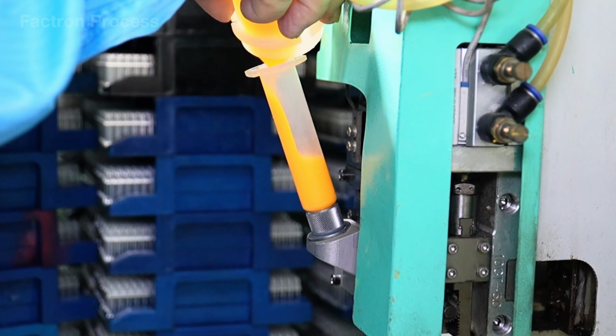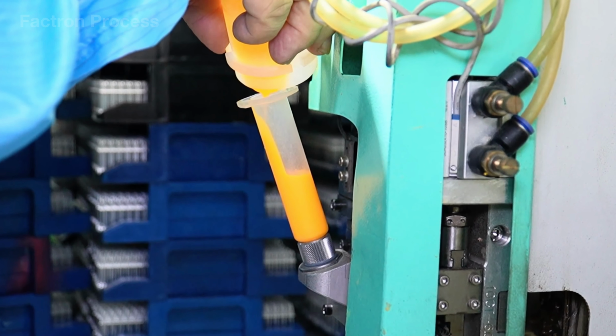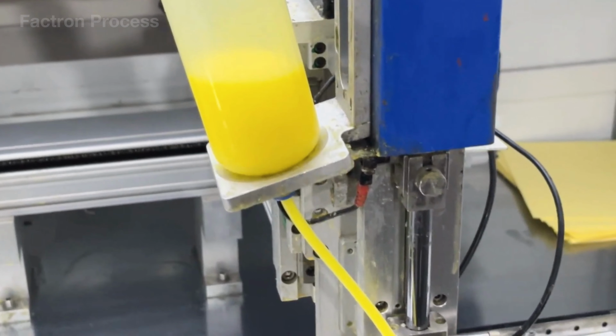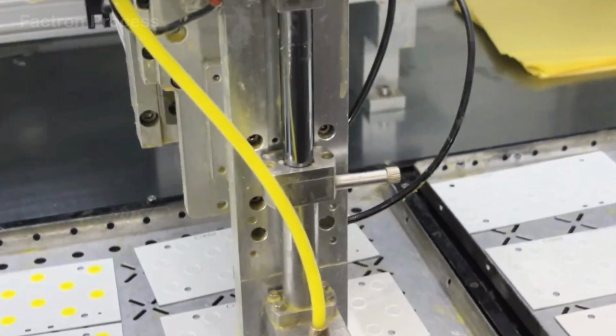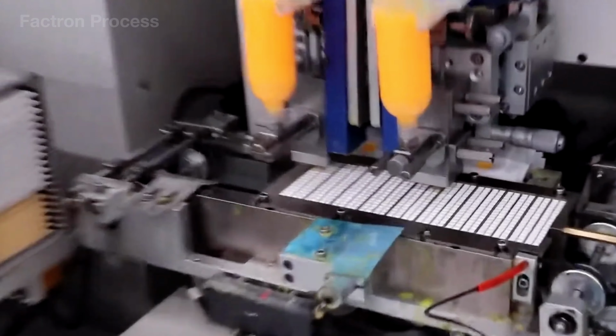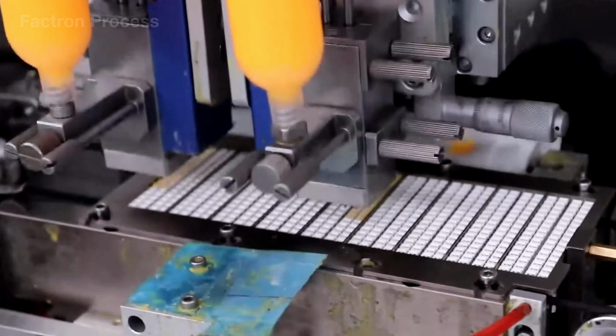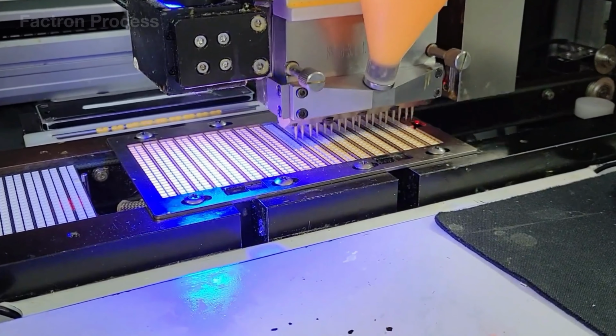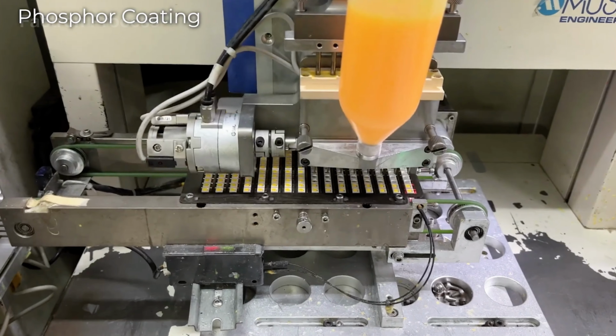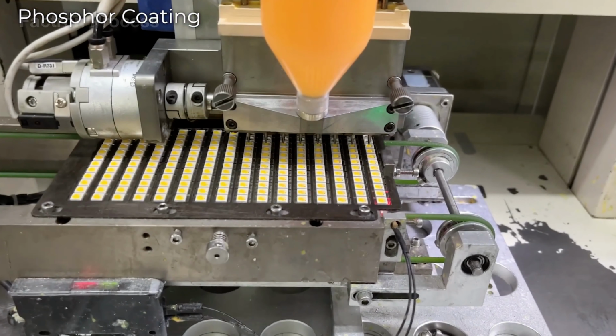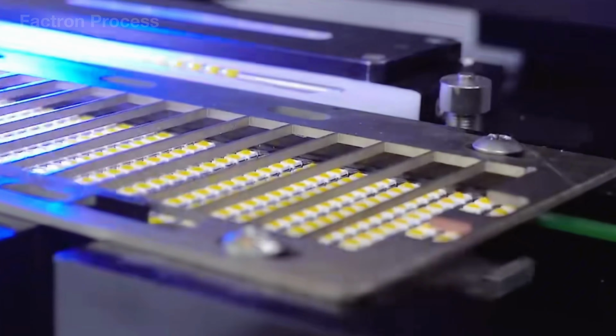The mixture is then loaded into the cylinder of a phosphor dispensing machine. Microscopic needles deposit an almost identical amount of the solution onto each chip, with volumes controlled down to millionths of a liter. Even the slightest variation can cause the LED to appear bluish, yellowish, or noticeably different from the rest of the batch.